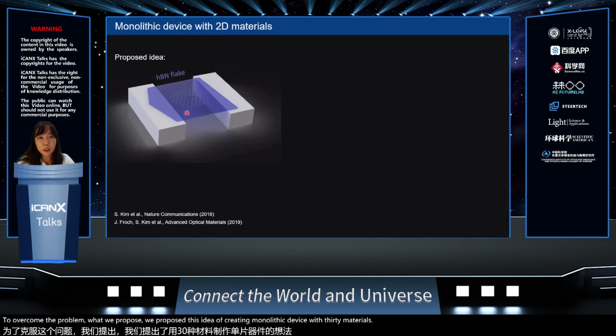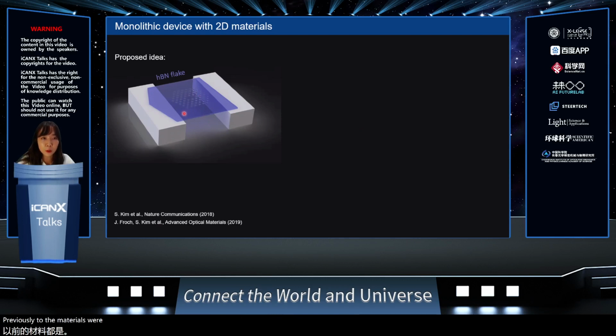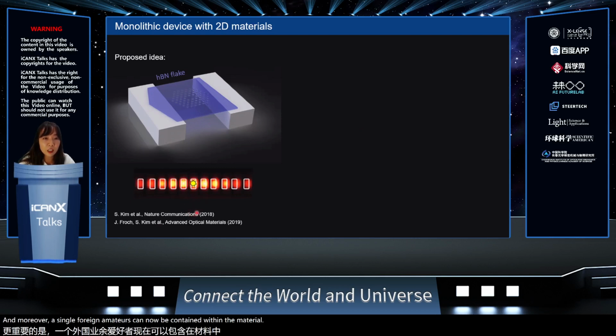Previously, 2D materials were transferred to an optical cavity in order to exploit the cavity effect. However, how about we just fabricate 2D crystals to create photonic devices? In that case, we can eliminate the transfer step, which is typically regarded as a not ideal technique for mass production. And moreover, single photon emitters can now be contained within the material, ideally coupling to the optical field maximum.